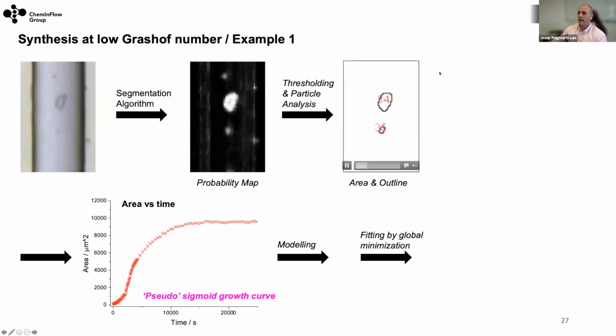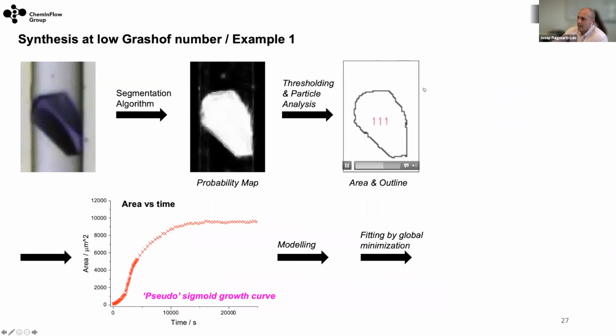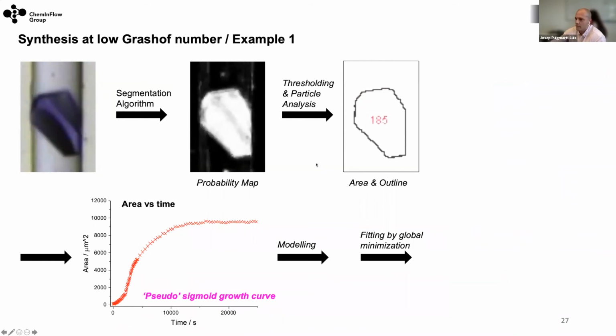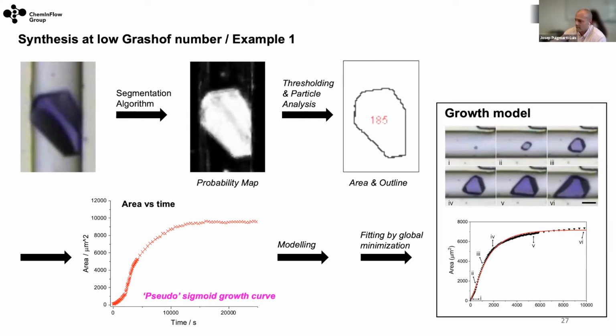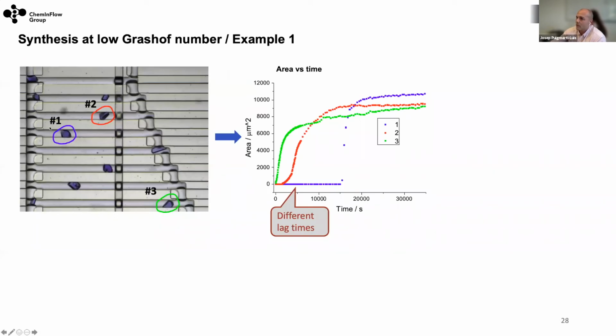We also did a segmentation algorithm that allows us to follow the growth of the crystal in these microfluidic devices. So then we have these area versus time plots. We did a mathematical model to extract all the constants of the growth, and this is how the fitting of our model looks with the experimental data. So it's very, very accurate. And what we see here is that, of course, we cannot really control when we want the nucleation to happen. This is clearly shown here.